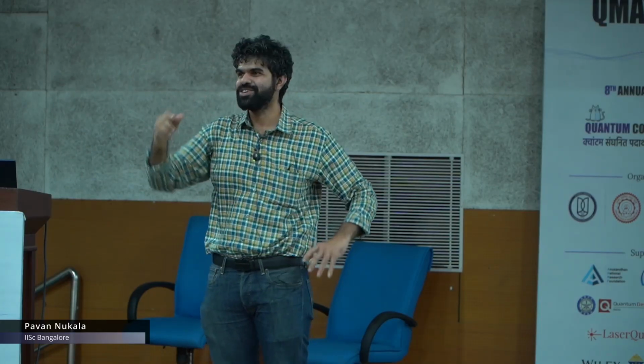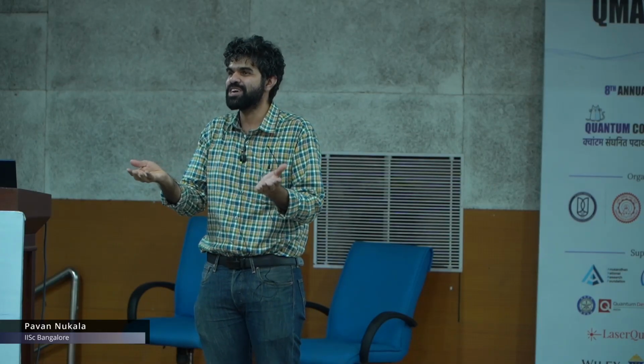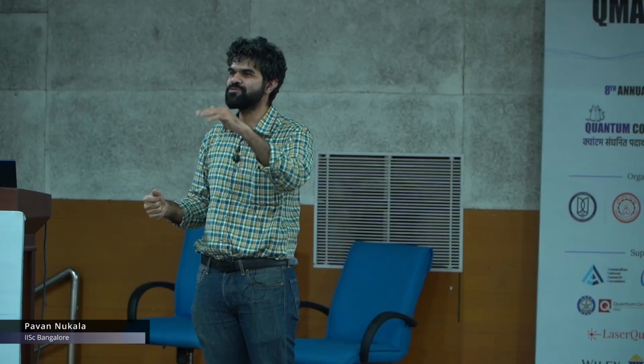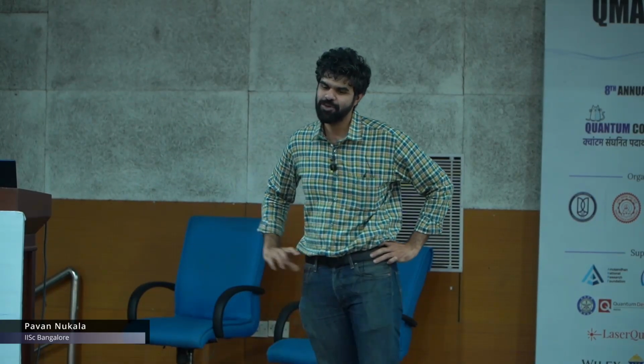But Joule heating also kills the piezoelectric coefficient. If I'm doing this on platforms where I don't have a good heat sink, then it's no longer 3 nanometer per volt, but comes down by some 1 order of magnitude. Yeah, current is a drawback compared to conventional piezo. Absolutely. I want to do everything with field, but current exists because it's a semiconductor, right?